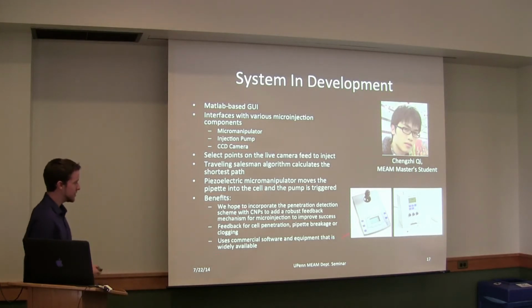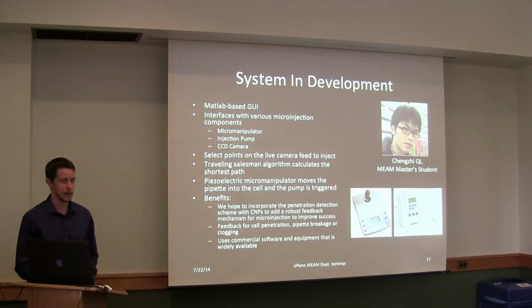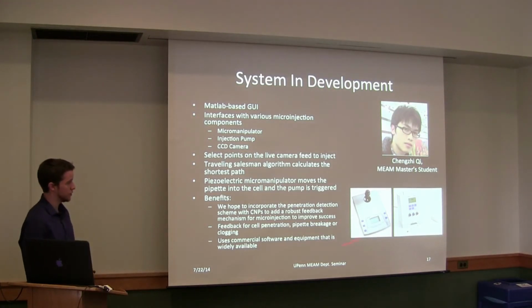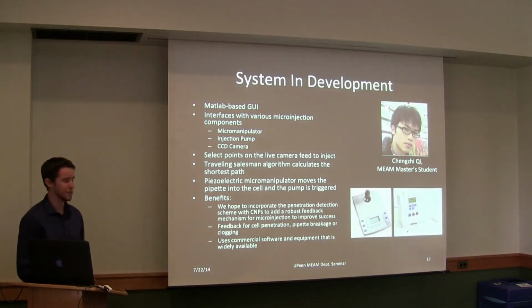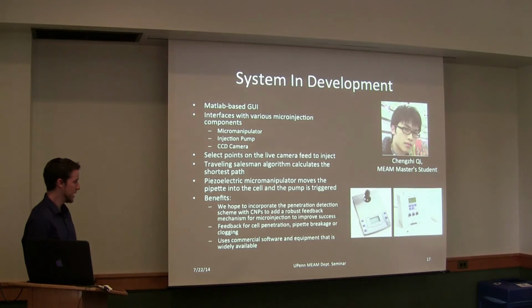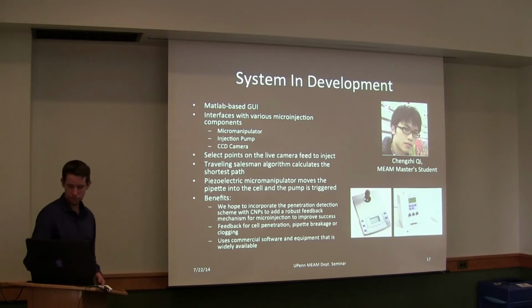But the benefits of this system are that we hope to incorporate this penetration detection to provide robust feedback of penetration, and also you can look at changes in the pipette due to breakage or clogging, which show up as signal changes as well. And it also uses commercially available software and equipment, since it's Matlab-based and we're using standard Eppendorf equipment. So it would be very applicable to many labs.